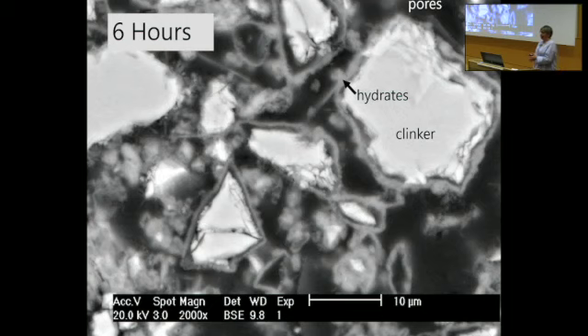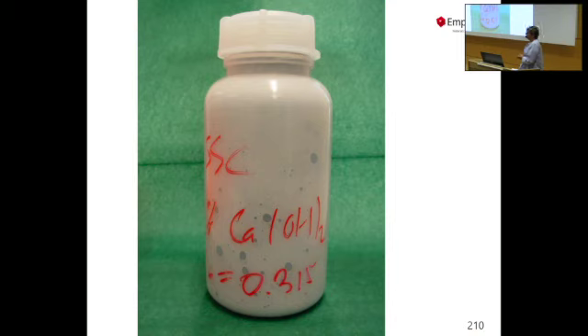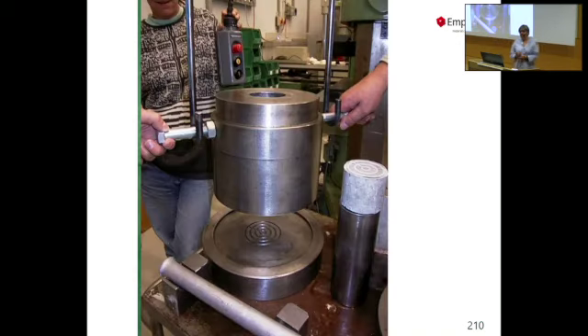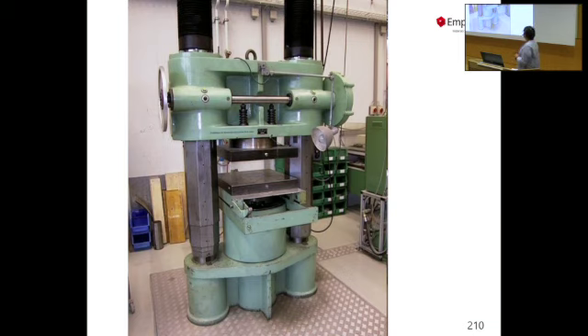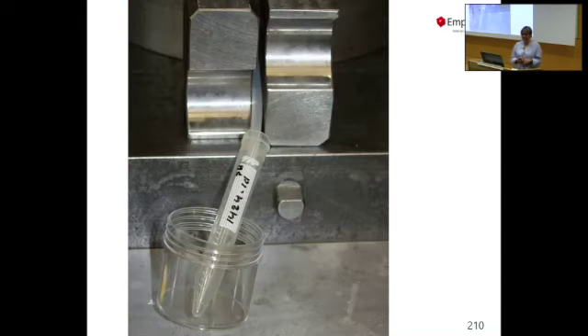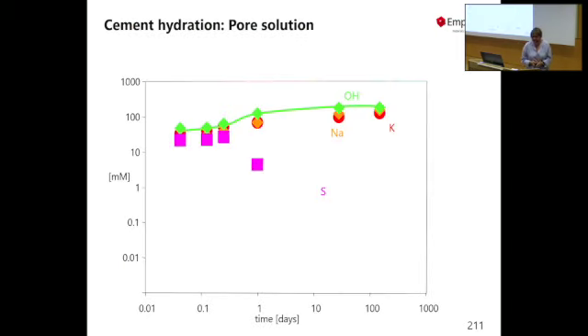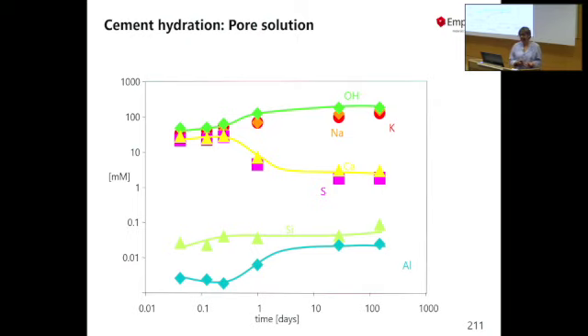You all know that. We can also do a completely different test, and that is pressing out pore solution. We hydrate a cement completely normally and keep it in plastic bottles because we don't want to lose any humidity. Then we put it into a big steel die, which you see here, and put that under the biggest press we have in the lab. It's a bit like pressing water out of stone. It works. You can collect some solution, maybe 10 milliliters per kilo, but you get something out, and you can analyze that. Normally you get a picture like that: a lot of hydroxide at high pH, a high sodium and potassium concentration, and initially also high calcium and sulfate concentrations, which go away as soon as you deplete your calcium sulfate carrier.